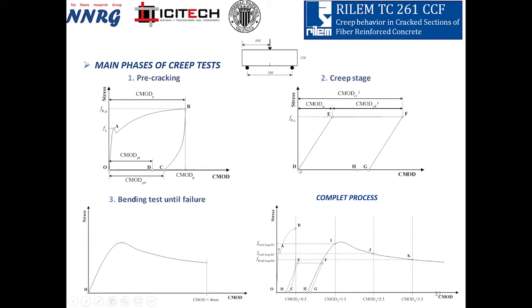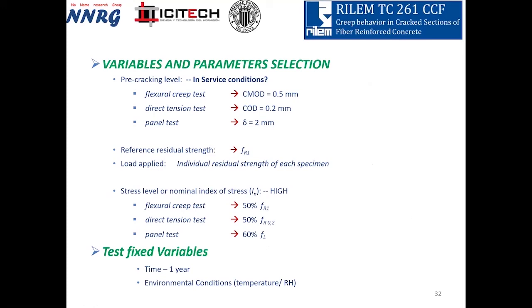Then, in the same conditions, we apply a similar load, a percentage of the residual capacity of this element. And then we conserve this load during a time. For this case, we use 1 year load application, creep stage. After the creep stage, we unload the specimen and reload until failure. We can organize a complete process like this: pre-cracking, creep period, and post-cracking until failure. Then we are able to evaluate residual capacity. Well, one of the points is what we want to analyze.